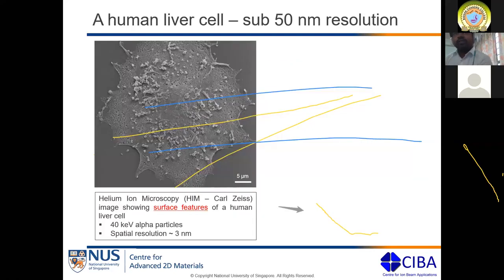Now this is an example of another microscopy, which I'll talk about later in my talk. This imaging is called helium ion microscopy, which has come up very recently. It is slightly different from what we do in CIBA. In CIBA, we use STEM, which is scanning transmission electron microscopy mode. Whereas in helium ion microscopy, you use a focused helium ion beam and scan over the surface of a cell or any sample, right? Then you generate secondary electrons because of the interaction with the primary beam. These secondary electrons are detected in a secondary electron detector, and from there you can see the morphology of the cells, as you can see here.